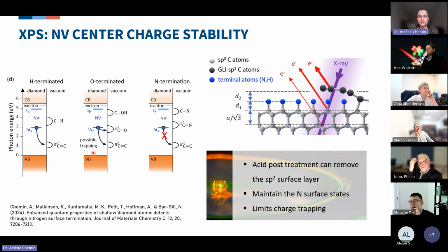But of course, if you do the measurement in an environment, you will have on top of this scheme and the possible trapping, the depletion layer happening. And that would definitely affect your NV centers too. One good example is that last time I was talking with a visitor in the lab who is doing NV center probing, and she told me, well, for some of the Kelvin probe tips that we use, when we put them under vacuum, they don't work anymore.